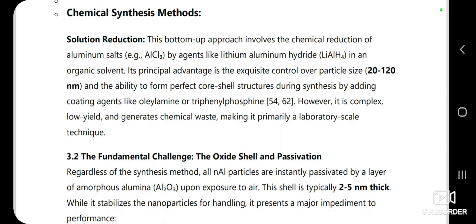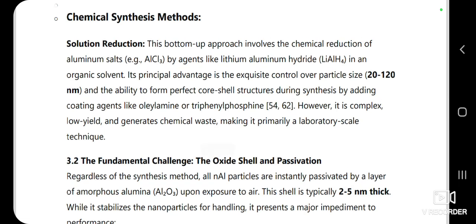And the next is the chemical synthesis method. It involves solution reduction. The bottom-up approach involves the chemical reduction of aluminium salts like aluminium trichloride by agents like lithium aluminium hydride in an organic solvent. Its principal advantage is exquisite control over particle size, 20 to 120 nanometers, and the ability to form a perfect core shell structure during synthesis by adding coating agents like oleylamine and triphenylphosphine. However, it's complex, low yield and generates chemical waste, also making it primarily a laboratory scale technique.